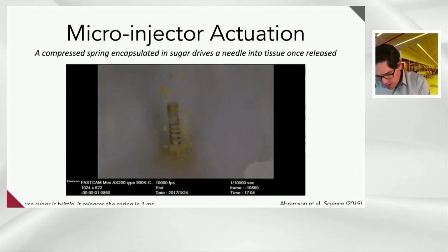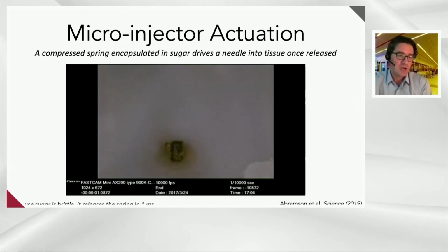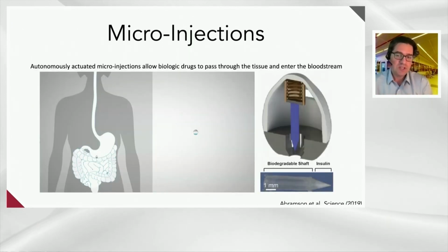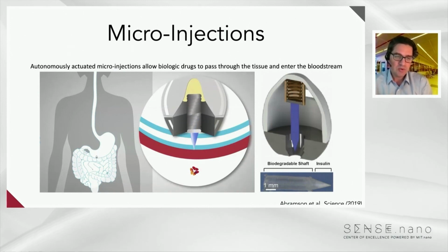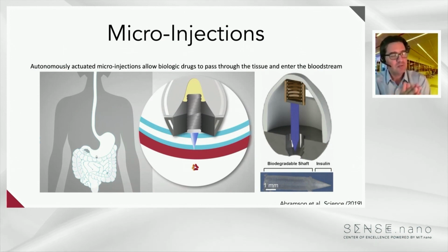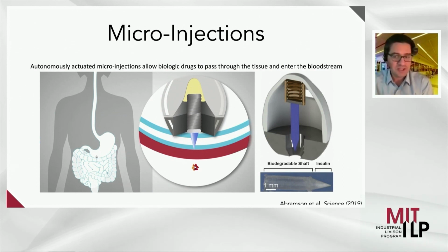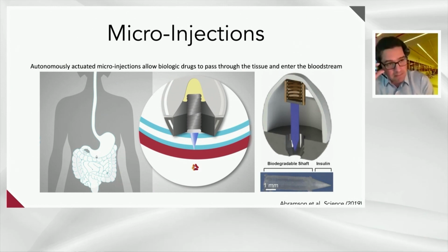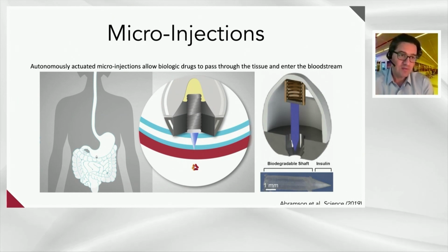And so number 3 was, how do we deliver a clinically meaningful level of drug? And one significant boundary condition here was that we wanted systems that were the size of a blueberry. And so we wanted that for safety. And so what we did was actually we shifted the drug formulation to maximize the density of the drug. Typically these drugs are in a liquid formulation, but we shifted to solid formulations. And we generated microneedles that contained anywhere from 80 to 100% of the active pharmaceutical ingredient, in this case, insulin.